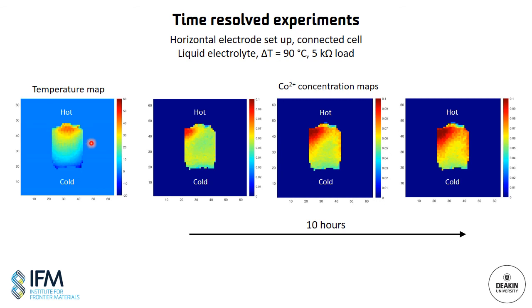And note that the top surface in these images looks a little bit distorted. And this is likely due to the presence of bubbles, which are unfortunately very hard to avoid in this cell. So after connecting the cell to a 5 kiloohm load, we can see the formation of cobalt 2+ concentration gradients that grow over time. You can see that it's quite a slow process and is still changing after 10 hours.